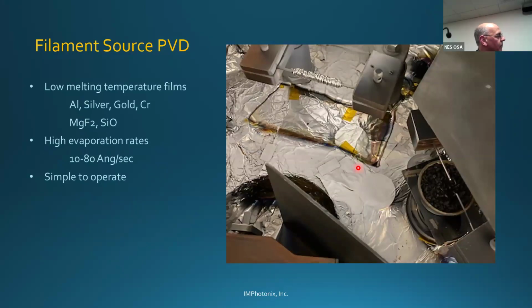Earlier, we talked about some of the metals that we do: aluminum, silver, and gold. Those are low temperature evaporation materials. Some of those films don't like to be evaporated with an E-beam gun. The E-beam is water cooled. It draws a lot of heat away from the source. And when you have a low temperature material, you're drawing heat away faster than you can actually apply it to evaporate the material. If you apply too much, it's going to spit and spatter. So